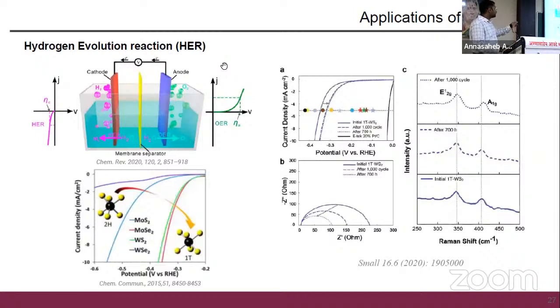Depending on the phases, the hydrogen evolution takes place more or less. In case of 2H, which is the semiconducting phase, this results in low formation of hydrogen. In 1T, the conductivity is higher due to the metallic phase. Here, higher performance is considered to be higher current, which is basically a higher number of electrons generated, which also reflects higher hydrogen evolution.